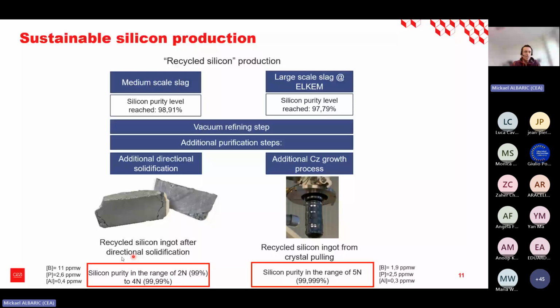You have to have in mind that within this recycled silicon, there is still some presence of dopants like boron, phosphorus, and aluminium in quite big quantity. Here I just put the numbers. For the other one, after the additional CZ growth process, they reach a purity of 5N with, here again, still a presence of dopants like boron, phosphorus, and aluminium. And in between the two growth steps, you can see that the boron concentration has been divided by a factor close to 5-6.